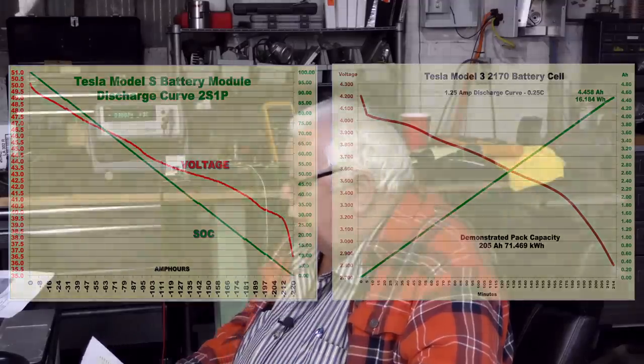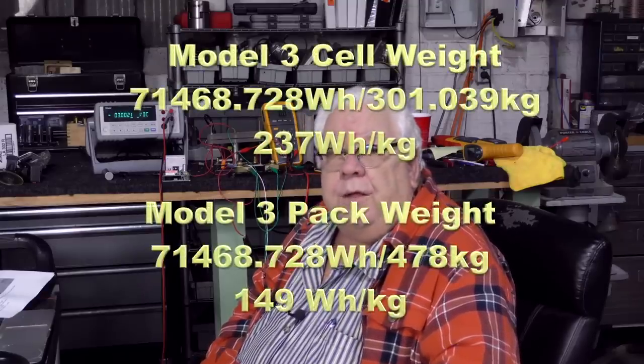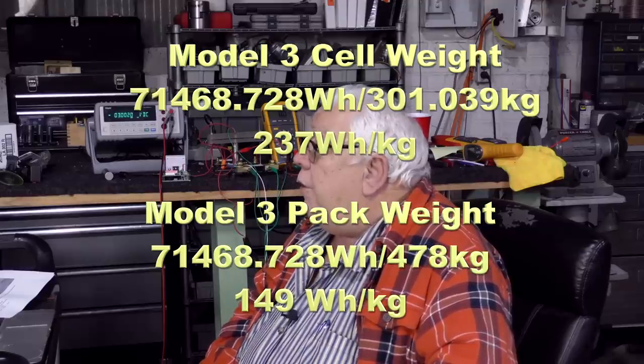Kind of surprising, 4.458 amp hours. I had guessed 4.8, and people were saying 5 to 6. That just doesn't appear to be the case. And our calculations show at the 4.458, you've got about 205 amp hours, I'm sorry, in a 46 cell Model 3 brick, and about 71,469 watt hours in the battery. And that all sounds pretty good to me.